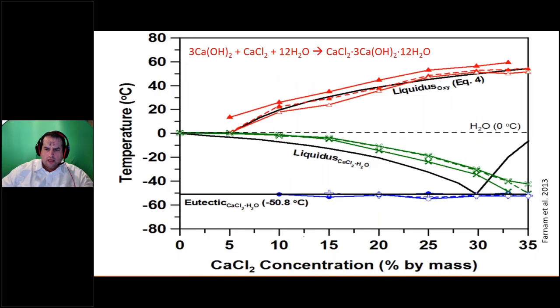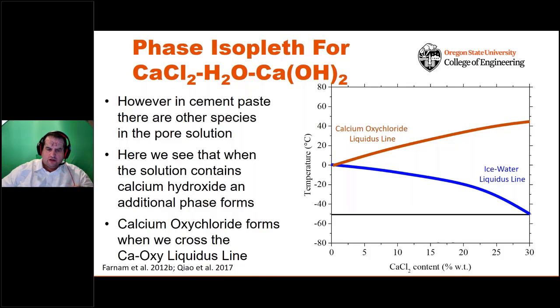Right, so the whole takeaway on this is we're going to look at this phase diagram, and what's been missing in the calcium chloride water phase diagram is the presence of that calcium hydroxide. That calcium hydroxide is a really important phase in this whole system, because what happens is if we're at high temperatures, again, we have salt water. But as we go across this orange line, what starts to happen now is we start to precipitate calcium oxychloride.